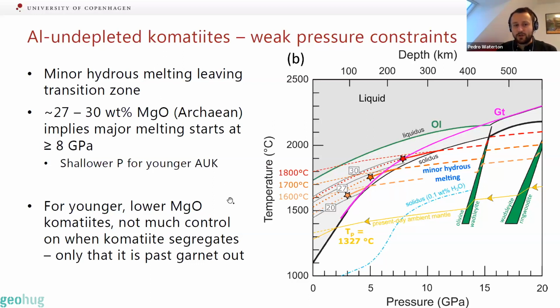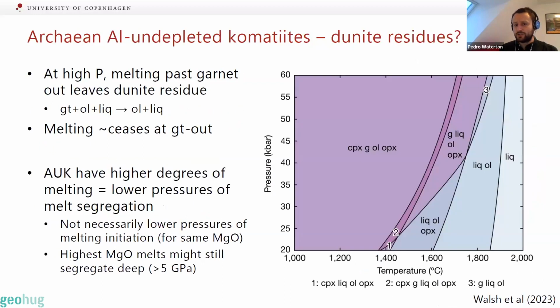Now, for these younger komatiites, we don't have much idea of where these melts would necessarily segregate. We need to melt past garnet out to get rid of the garnet signature. But at low pressures, after you melt past garnet out, you still have a residue of harzburgite, olivine plus OPX, and so you can actually carry on melting. At high pressures, it's quite different. The reason for this is that garnet is the next mineral down from olivine from the liquidus. So when you go from melting garnet plus olivine to just past garnet out, you're basically trying to melt a pure olivine dunite composition, and the melt productivity drops tremendously.